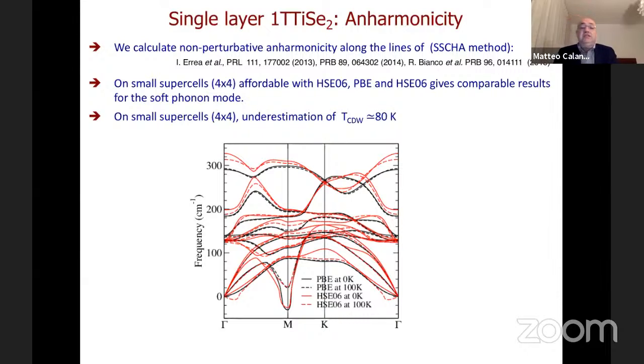Unfortunately, with HSE06 we couldn't do more than 1,000 calculations on 4x4 for each temperature. I remind you that 4x4 means 48 atoms with no symmetries and k points. And so what happens is that if you take PBE or HSE06, you get essentially the same result for the soft mode.